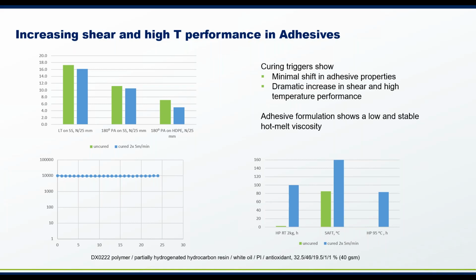And this is just some of the data that shows that the properties are still somewhat similar. So before cure, the tack is still similar, and the peel adhesion is still similar on different substrates. Here we have stainless steel versus HDPE. Even when it's uncured, the hot melt viscosity stability is still relatively stable over, at least in this case, 24 hours. And again, the big key here is once we cure it, it provides a much higher temperature for the application, such as SAFT and better holding power as well, compared to an uncured system.